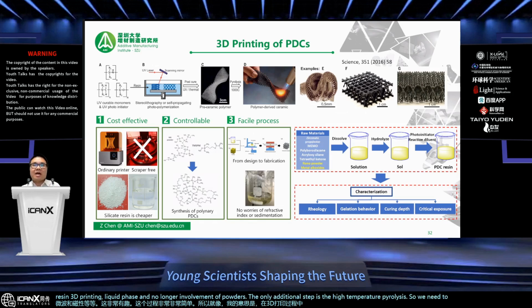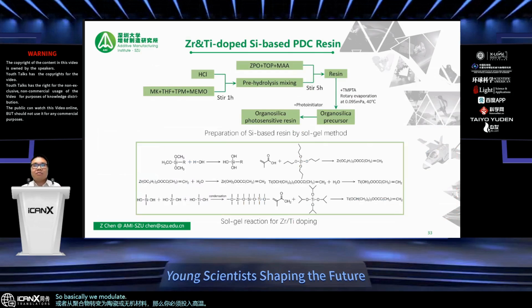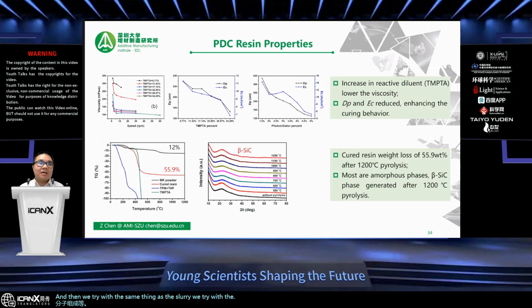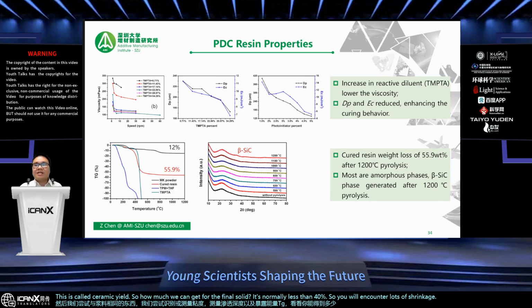Like sintering, you have to get the transformation from polymer to ceramic or inorganic material, so you have to put it in high temperature. Basically, we first modulate our own recipes, which is relevant to the chemistry side, and we put much effort into controlling the molecular compositions. And then we treat it the same as a slurry. We identify or measure the viscosity, the penetration depth, the exposure energy, and TG, to see how much you can get, which is called the ceramic yield. So how much you get as the final solid is normally less than 40%. So you will encounter lots of shrinkage during the whole process at high temperature.